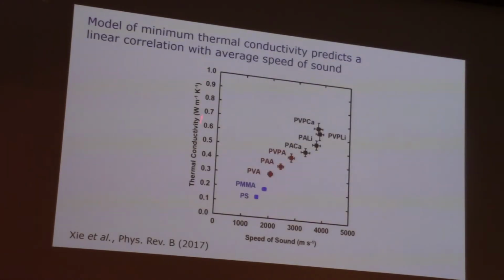And if I organize the thermal conductivity we measured for these materials versus the speed of sound in the materials, we should get something like a factor of 3 range, square root of 10, and that's basically what we see. So everything works pretty well. The minimum thermal conductivity model would just predict a straight line going through the origin. Polystyrene is a little bit below that, but as we go here, it turns up a little bit. But the maximum we get is about 0.6 watt per meter Kelvin for these kinds of amorphous polymers. Actually, we're still working on this kind of thing.